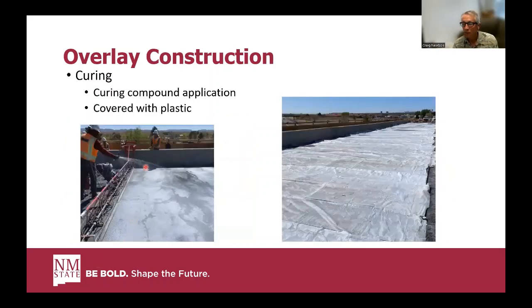When it went well, the curing compound was going down right behind the screed, and the plastic was getting put down no more than a handful of minutes behind the curing compound. When that happened, everything went well. At worst, we got isolated cracking. You could walk several yards of the deck before you could actually find a crack. So things went well when this practice was incorporated.